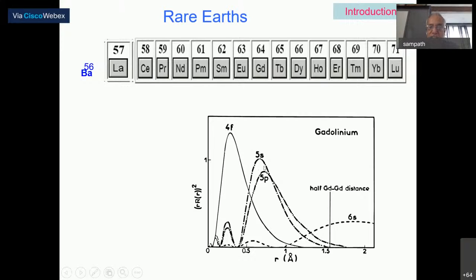Of course, the 5d and 6s electrons participate in bonding. So it was believed for quite a long time that the 4f orbital cannot participate in bonding. And now it is recognized, from work carried out 4 decades ago, it is now generally accepted. There is enough evidence today that this is no longer true when it comes to light rare earths like cerium, to some extent also praseodymium and neodymium. There is some degree of delocalization because of which you find a whole lot of phenomena in solid state materials. However, now it's accepted that this problem does not exist in the middle of the series,